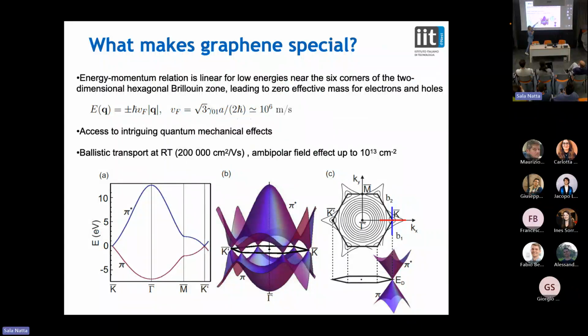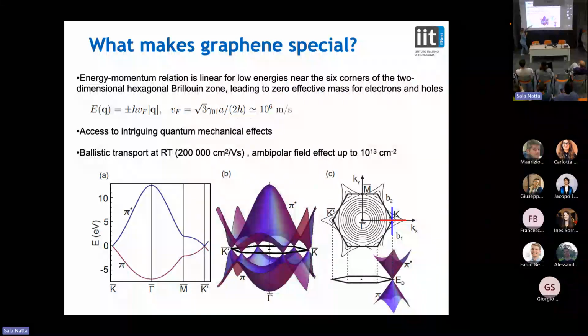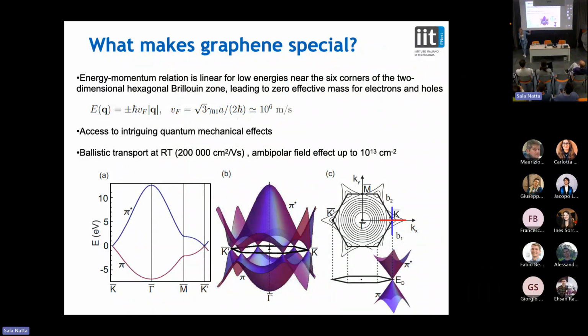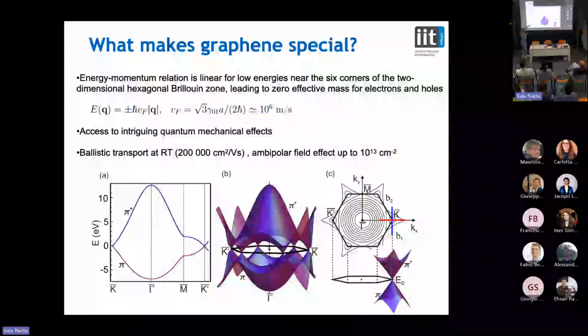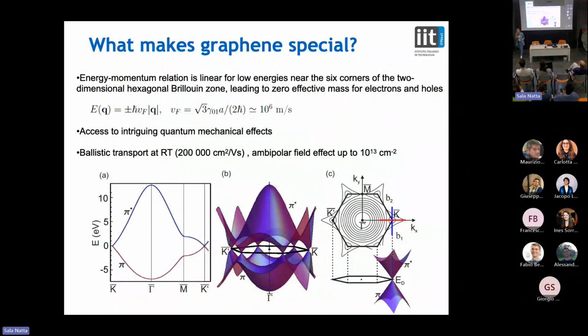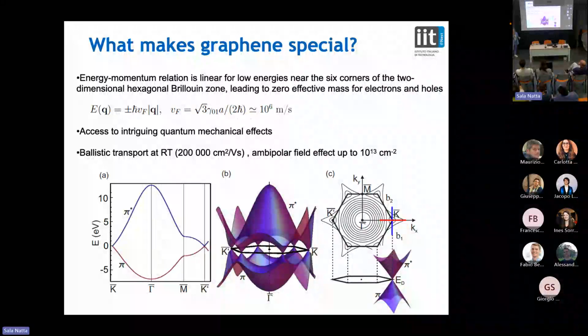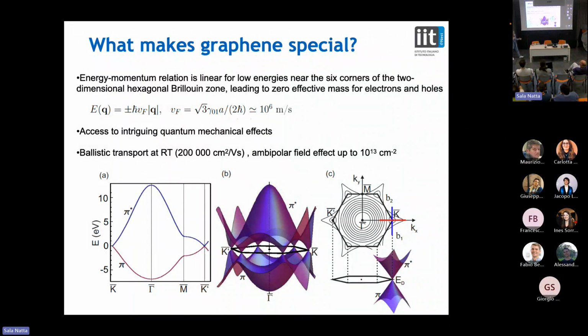And this is what really makes graphene special, because that means that the electrons, the carriers, in our case also the holes, because graphene is bipolar, as both electrons and holes conduct very well, have a zero effective mass. That means that these particles move within this material at incredible velocities, which have often been said to be similar to those of light. Okay, it's not really true, but actually they are very high velocities. Mobilities of electrons in graphene can very easily go to 200,000 centimeters squared per volt per second, which is a very, very high velocity. So this guy moves ballistically. That's basically the major point.